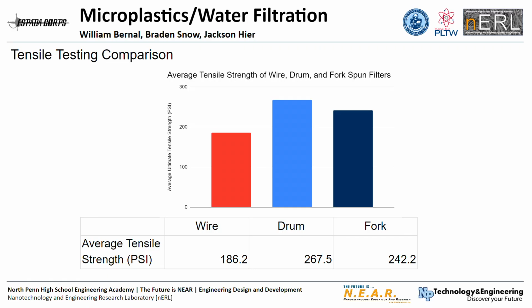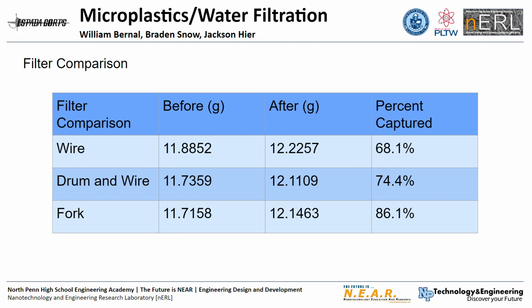And when we start comparing the average tensile strength of all of the filters that we use, it is clear that drum spinning was the strongest. And unfortunately enough, the wire spinning fell almost 80 psi behind, while the fork spinning was just 20. Following a similar theme in terms of filter efficiency, we found our wire efficiency was the lowest, with fork being the highest at 86.1%, with drum spinning not far behind. Quite frankly, for these level of filters that we're making, that's a staggering number to be removed.